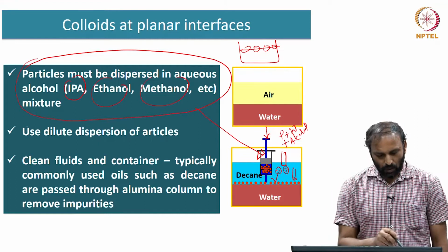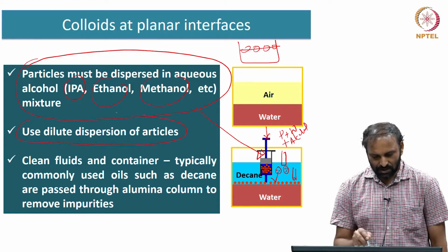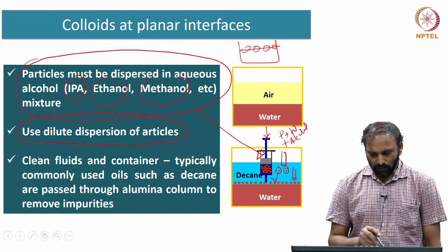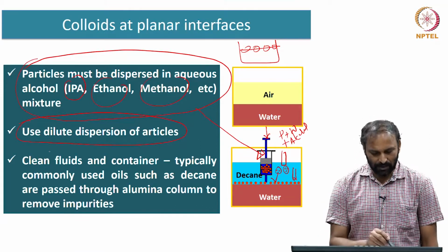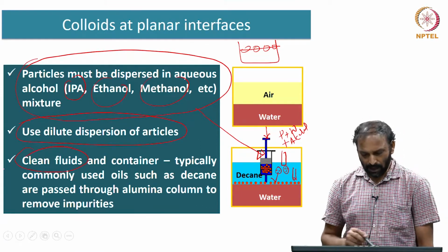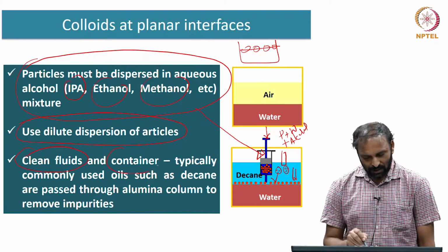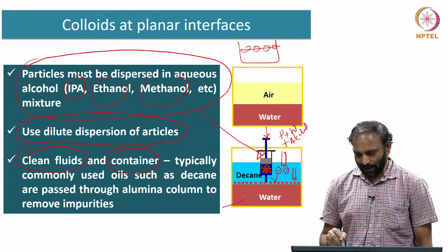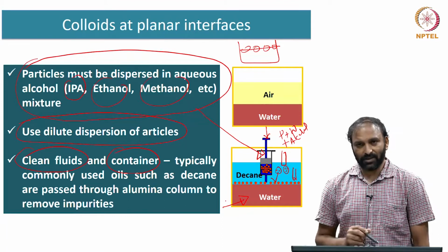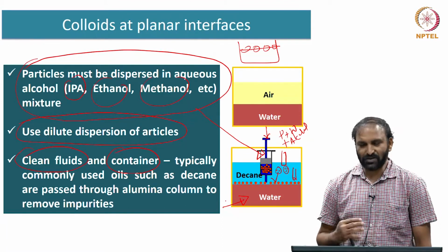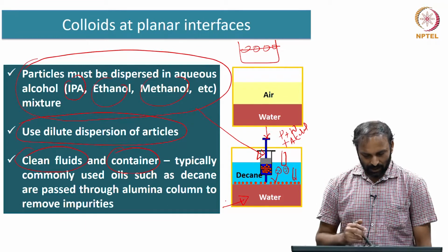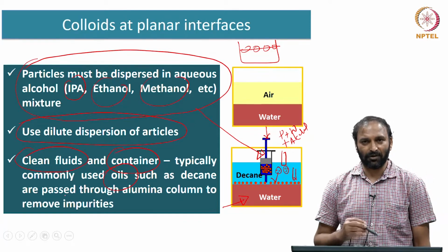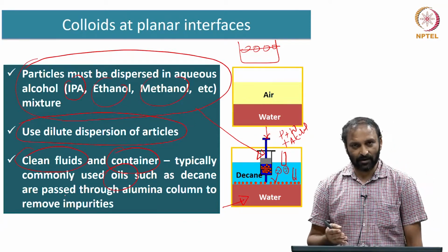Of course, one has to work with very dilute dispersions, and another important consideration is that the fluids being used for these experiments have to be extremely clean, and the container also has to be extremely clean. What I mean by that is that it is good practice to use double distilled water which does not have any ions present, and you should ensure that there are no surface active additives in the oils.